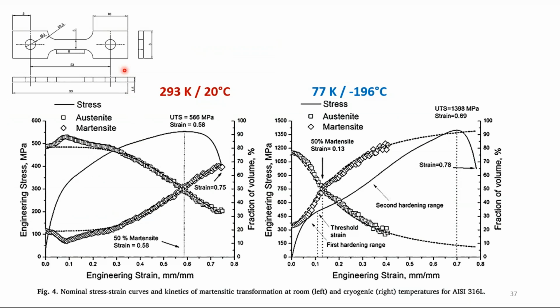They used a stainless steel, a 316L steel. And you have here the conventional engineering stress and strain curve, this black one here, for two cases: at room temperature and at minus 196 degrees Celsius.